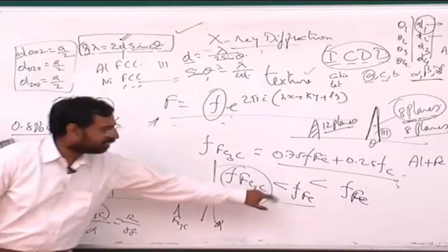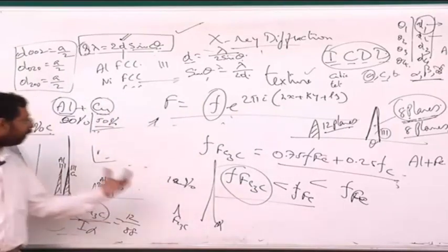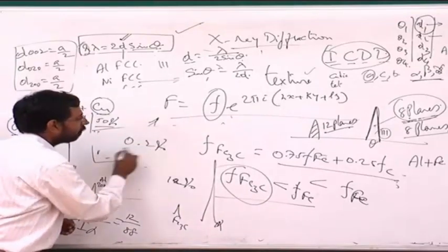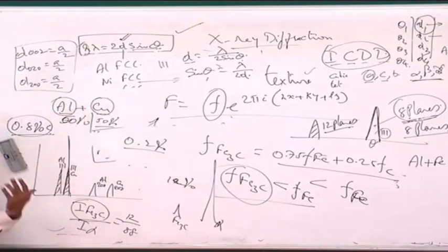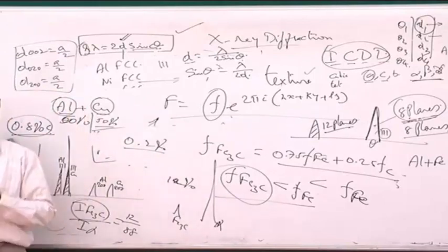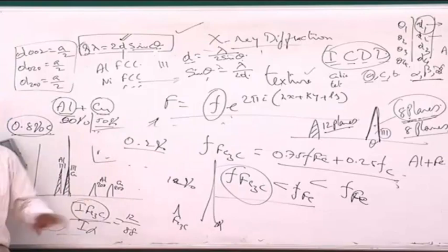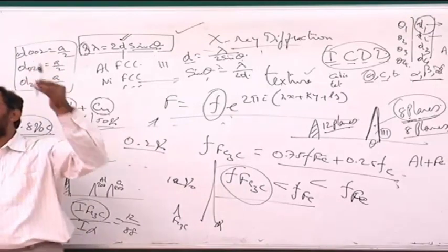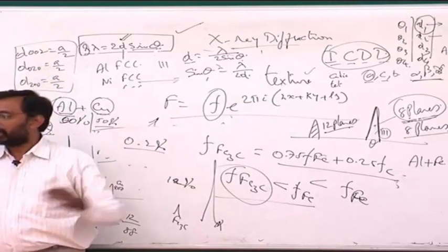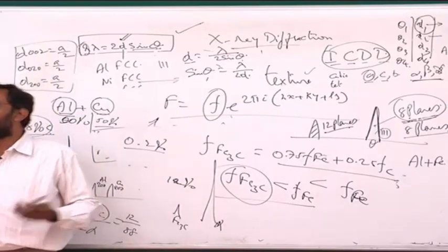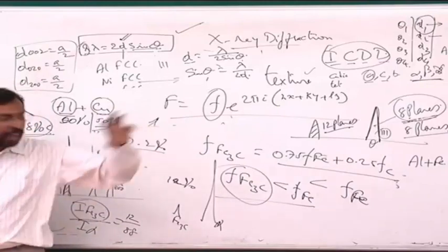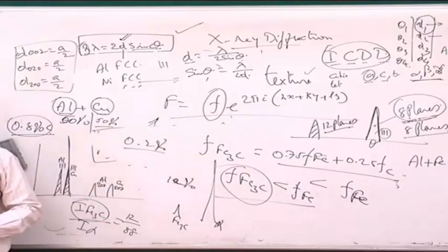The reason is this. And if I'm talking of 0.8%, or if I take a mild steel, 0.2% carbon steel, obviously the cementite is much smaller, and as a result you may not see any Fe3C. So for an XRD, it looks as if it is pure iron. And I do chemical analysis and I find no, it is not so. And I do optical microscopy, and I see yes, there is cementite inside. But I don't see cementite in the XRD pattern.